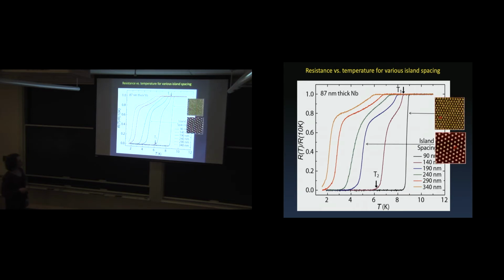And so you can see that for the very closely spaced islands, we get one transition. These are close spaced by 90 nanometers. We expect the whole thing to go superconducting as soon as we hit the TC of niobium. That's exactly what happens. And notice that it goes superconducting around 9 Kelvin. So that tells us that there's nothing funny with niobium. There's nothing weird. It basically acts like a film of niobium. Right? We're not getting inverse proximity effect or anything like that. And then as we increase the island spacing, the transitions go to lower and lower temperatures, which is what you might expect.